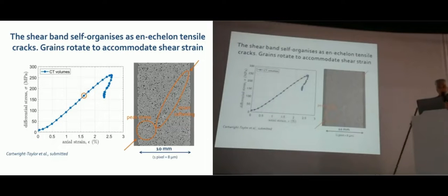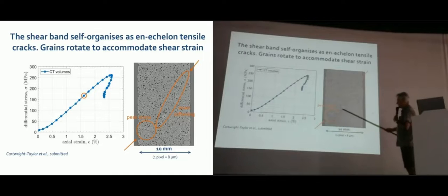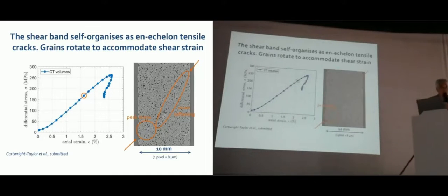So you don't really get nucleation of the shear band. That comes later. The first thing that happens is that these tensile cracks align across the sample virtually instantaneously. And this is what makes failure hard to predict. How would you know from the measurement immediately before that point that that was going to happen? It's really a very, very nonlinear process, the localization.